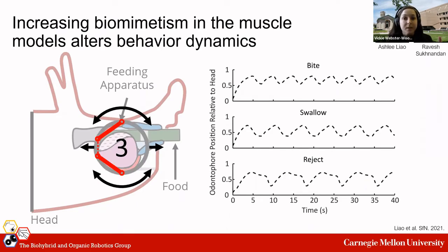We can replace the muscle models with more biomimetic muscle models. In our original model framework, we just used low pass filter approximations of smooth muscle. However, we can replace those with more complex models. For the I2, for example, there's a Hill-type muscle model in the literature that we were able to test. And in simulation, this had the largest impact on the model dynamics. So moving forward, we're now actually working on characterizing more of the muscles in the system so that we can add those to the model as well.